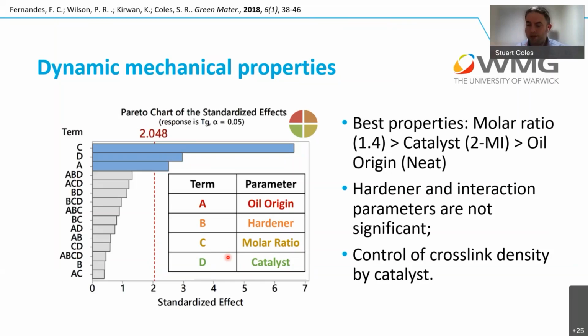And this was one where we saw the data and we largely threw it out the window because we wanted to use the waste oil. It was like, yes, we know that the neat oil will get us a better one, but what if we use the waste oil? How far can we push it? The other two we optimized and kept in our formulation. We followed through with the 1.4 molar ratio of hardener to epoxy, and we followed through with the use of 2-methylimidazole as our catalyst. But most of the other things we then left.